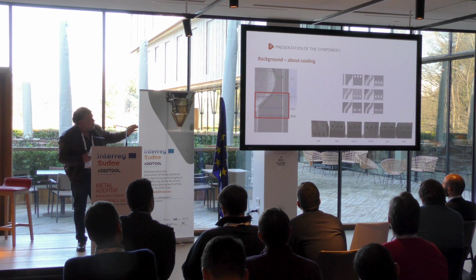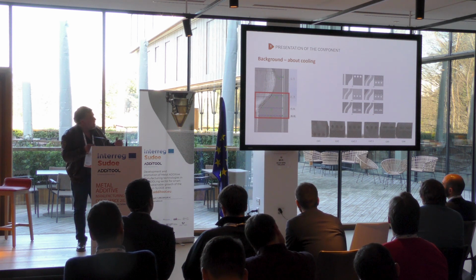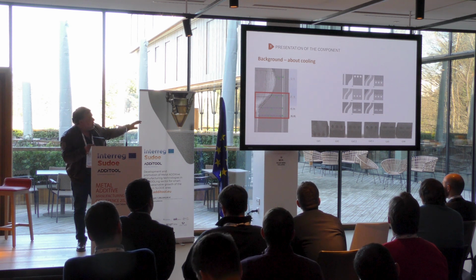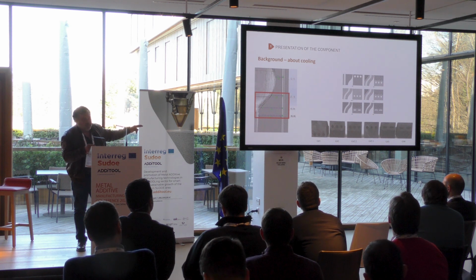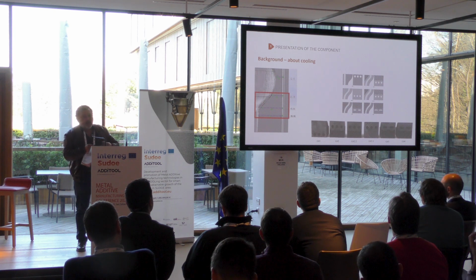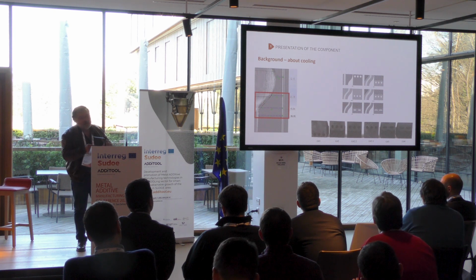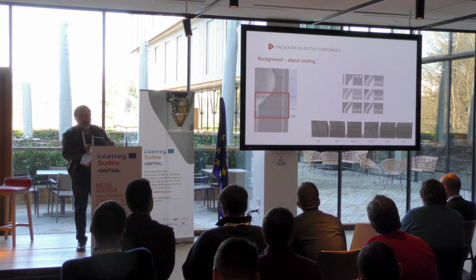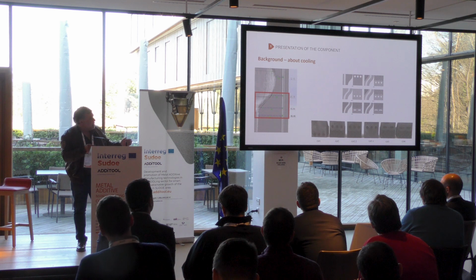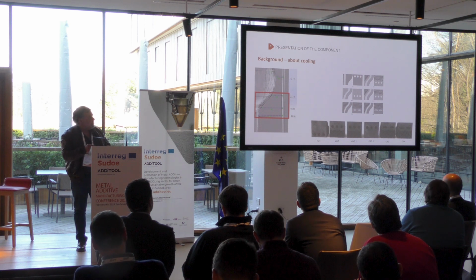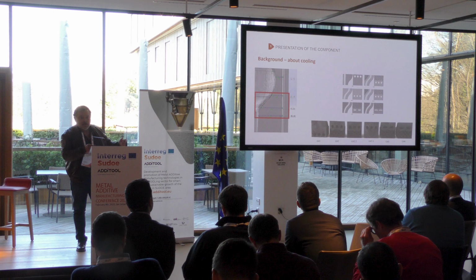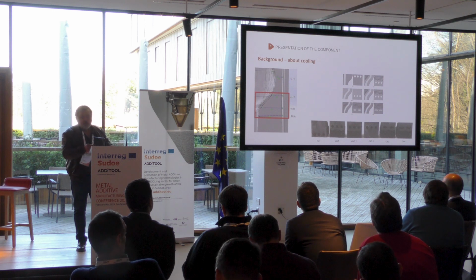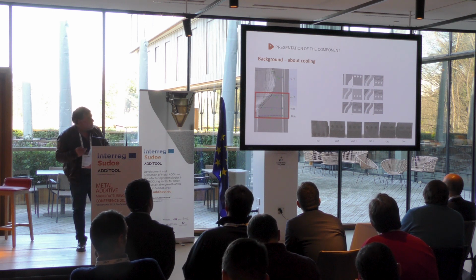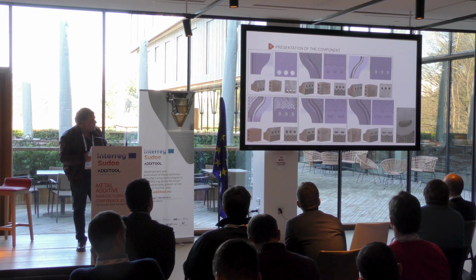We need to perform some testing on geometries, so we look at a curved part of the bottle to get some samples with different geometries. We test it using acquisition from FLIR, imposing heating on the sample and also cooling with airflow. We made a lot of tests.